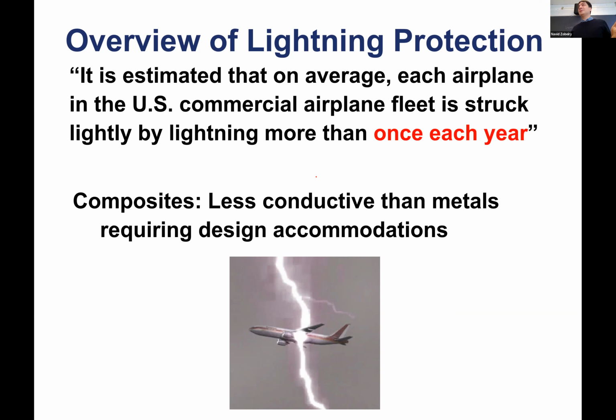So lightning strike happens. How do we guarantee the survival of composites, keeping in mind that this event happens in 2 microseconds? First of all, from a simulation perspective, we are very limited. I've talked to people who are experts in this at Boeing. They have done this for 30 years. We still heavily rely on tests. There are test setups that can simulate the lightning strike. We used to have one here at UW in the AA department, and the PI left and took the machine with him. But it's a very cool test.